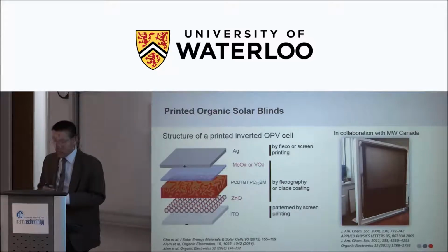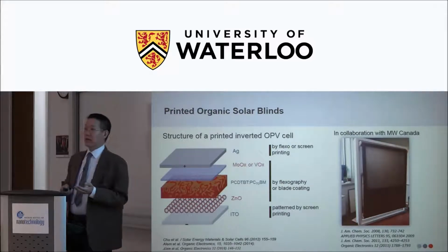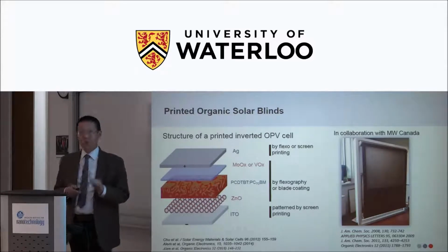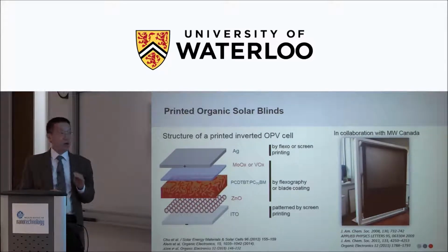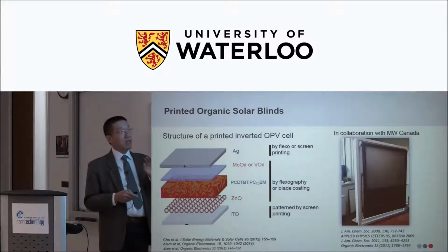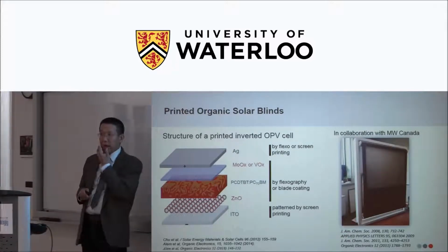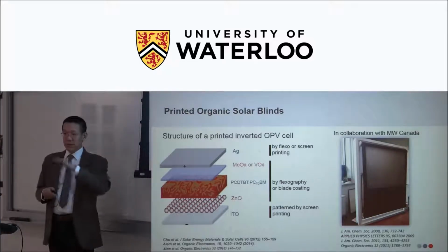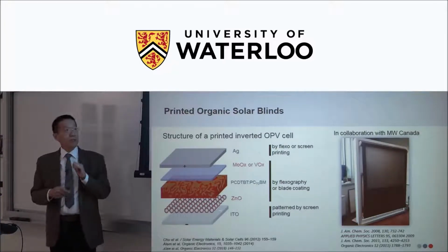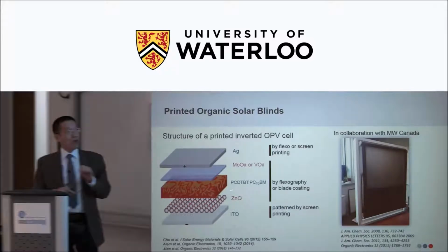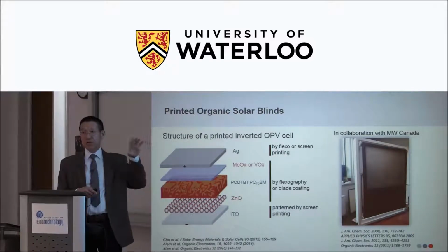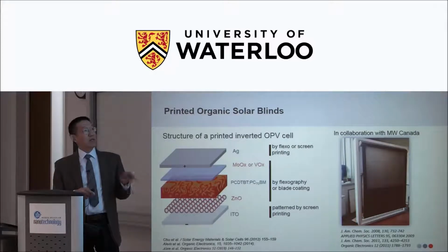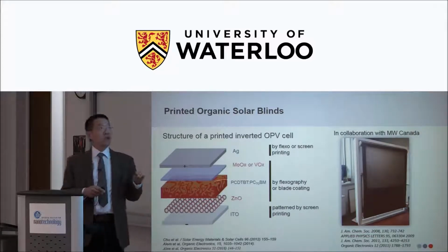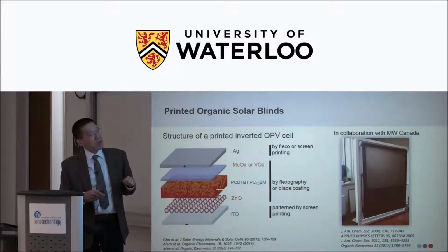We also worked on printed organic solar cells. It is a relatively reasonable actual product for printing technology. What we did here was develop a zinc oxide nanoparticle ink that does not need high temperature annealing. So when you put it down, it forms a dense zinc oxide film that will not be dissolved by the solvent we use for the active layer. Then we developed a printable vanadium oxide on top of that. Using the printing process of flexo and the slot die coating process, we made different types of solar cells.